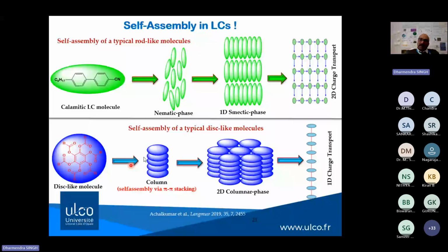So in contrast to these calamitic materials, if you talk about the disc-like molecule, they self-assemble into columns first via pi-pi stacking. Please remember that this pi-pi stacking and self-assembly arrangement of these disc-like molecules is completely spontaneous. You cannot influence this pi-pi stacking as well. And depending on the geometrical conditions and other environmental conditions, they can be arranged into a hexagonal matrix, rectangular matrix, oblique matrix, and so on. This depends on the crystallographic conditions.